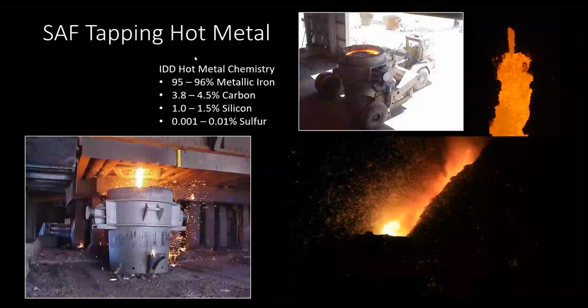So when we tap, our hot metal coming out of the submerged arc furnace is 95 to 96% metallic iron in liquid form. It's between 3.8 and 4.5% carbon, between 1 and 1.5% silicon, and relatively low sulfur content.